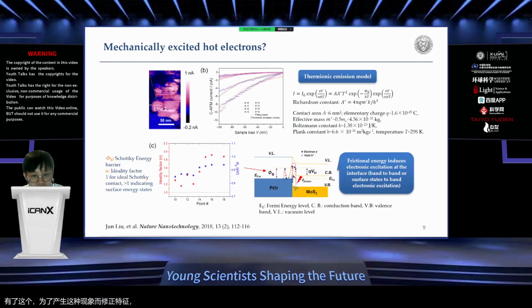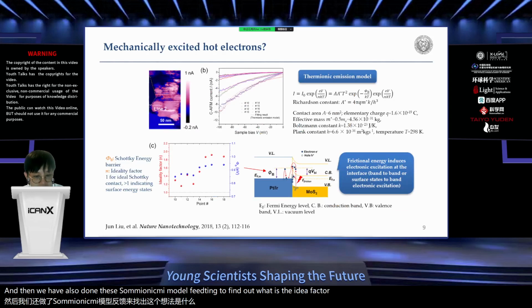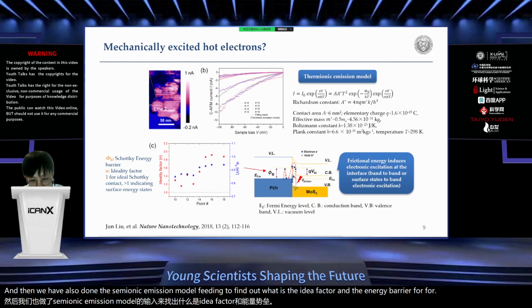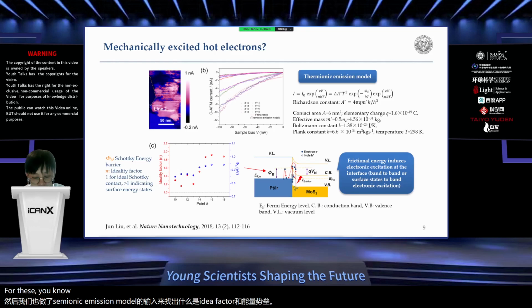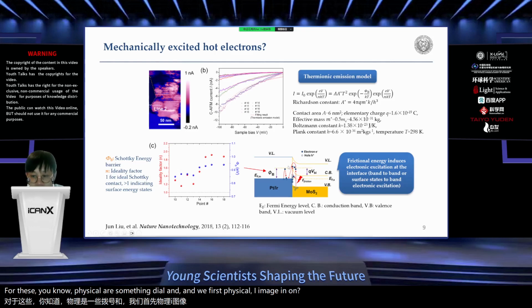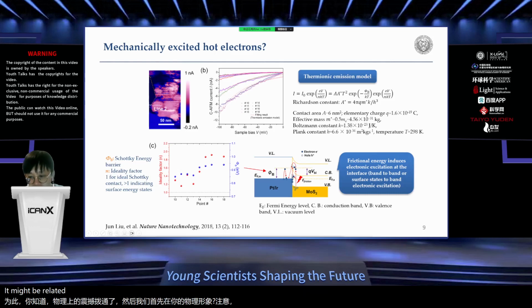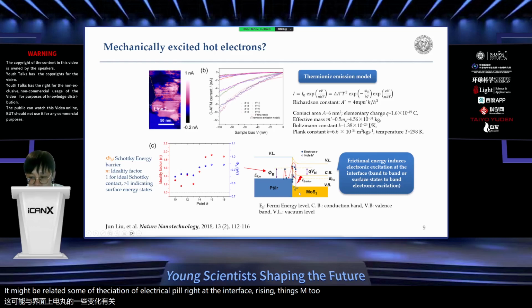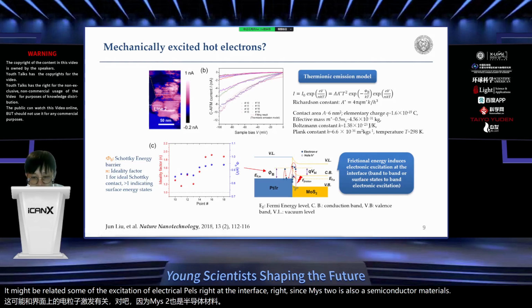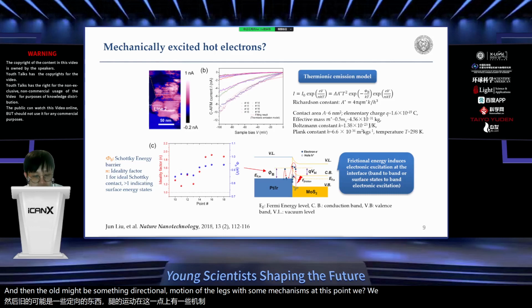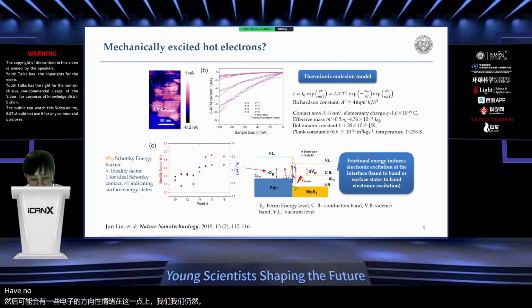And then we have also done the thermionic emission model fitting to find out what is the ideality factor and the energy barrier for this physical Schottky diode. And then the first physical image in our mind is that it might be related to some of the excitation of electron-hole pairs right at the interface, right? Since MoS2 is also a semiconductor material, there might be some directional motion of the electrons with some mechanisms. At this point, we still have no very clear answers.